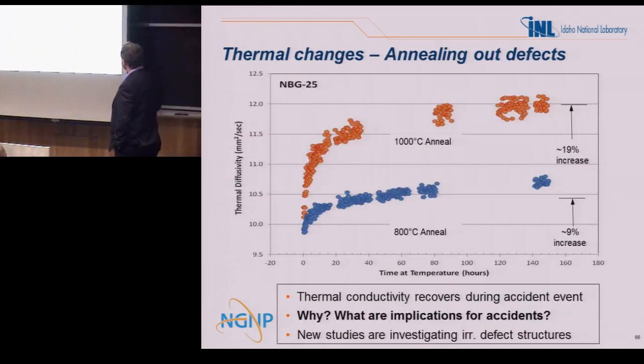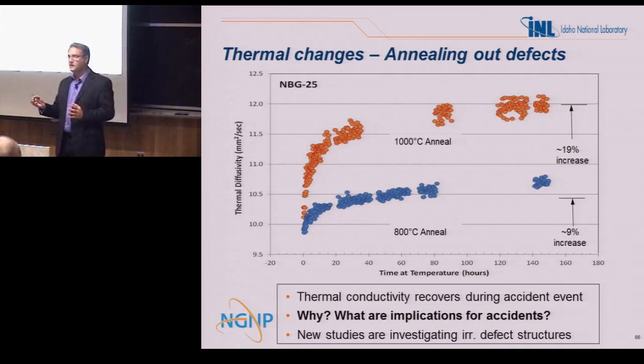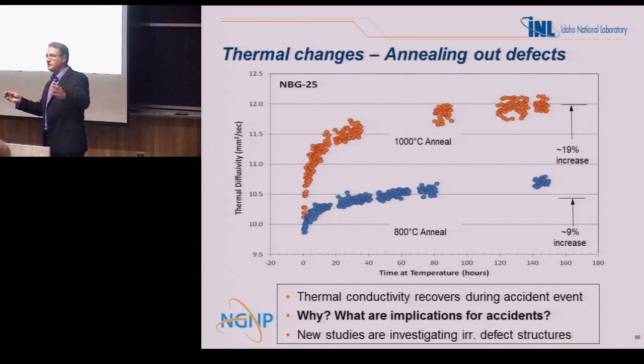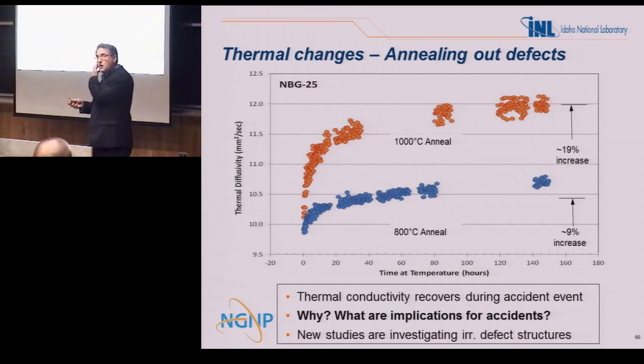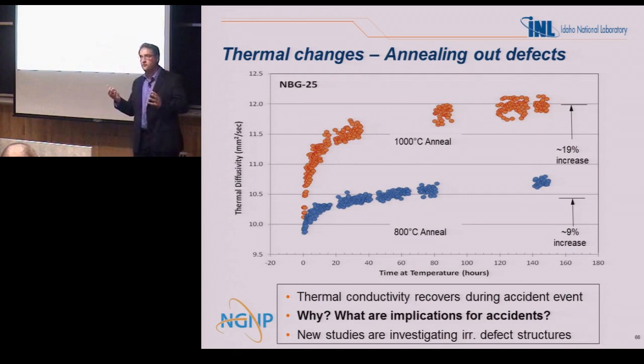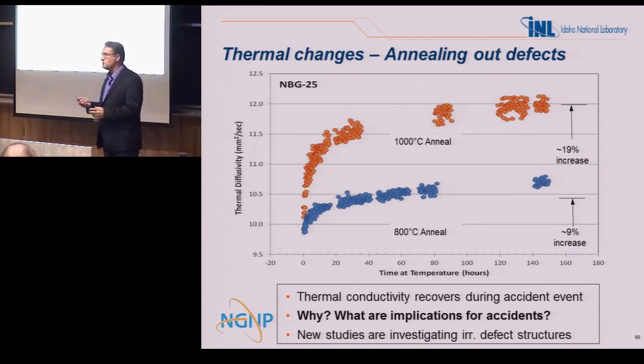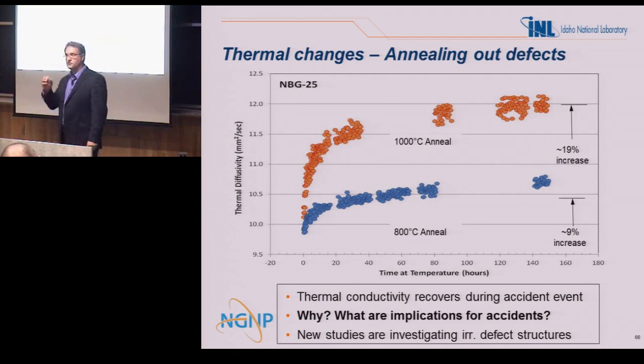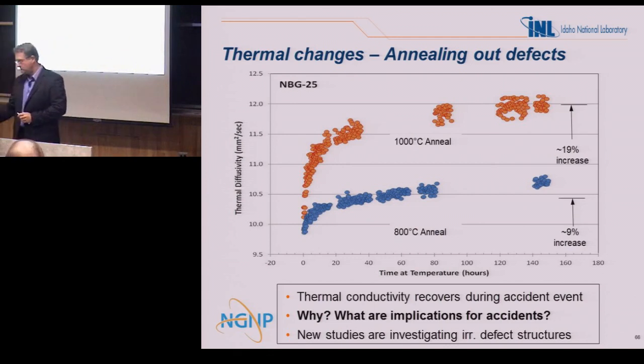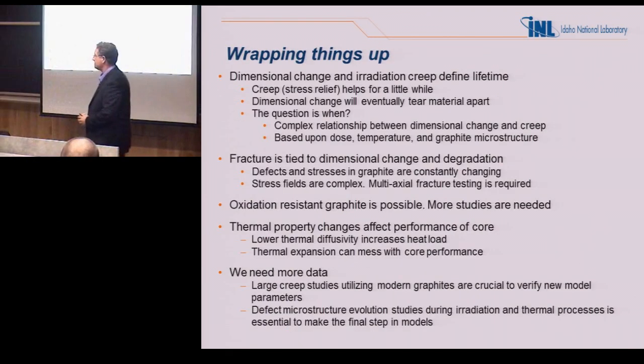Finally, thermal changes. What's interesting is that with a little bit of heat and a little bit of time, you can actually anneal out those point defects, and so the thermal diffusivity and conductivity starts to recover. How long? Well, most accident scenarios predicted for these kinds of reactors are about 100, 120 hours. Well, you can get up to almost a 19% increase in the thermal conductivity that gets that heat out because you're not introducing more defects from irradiation.